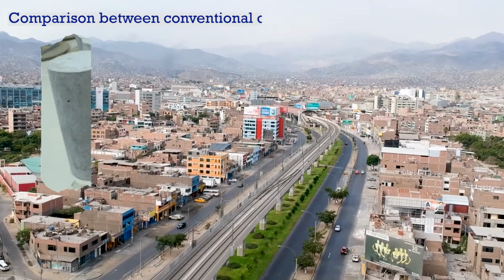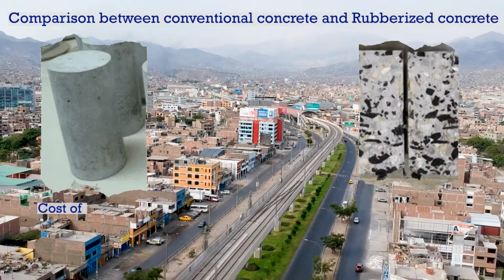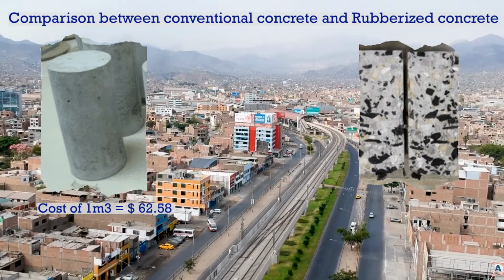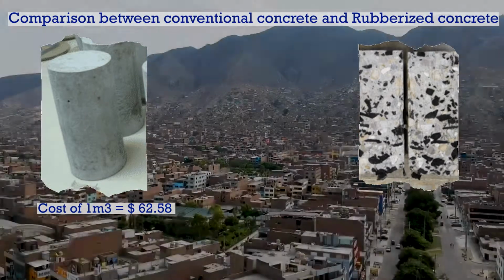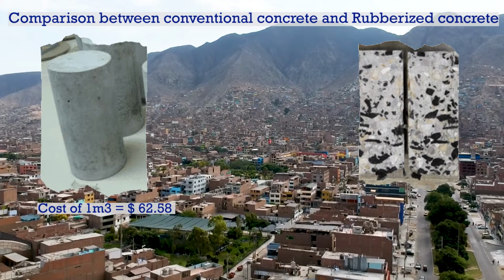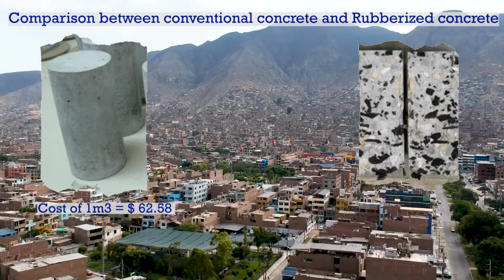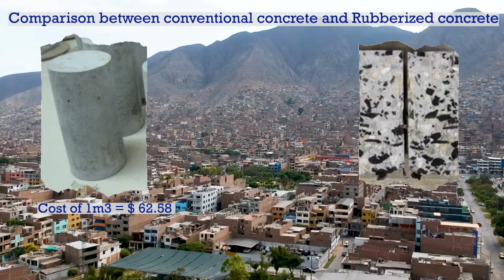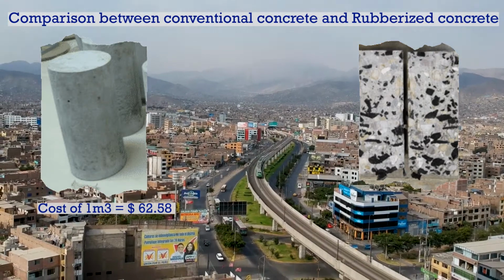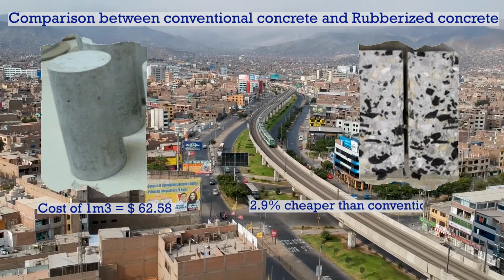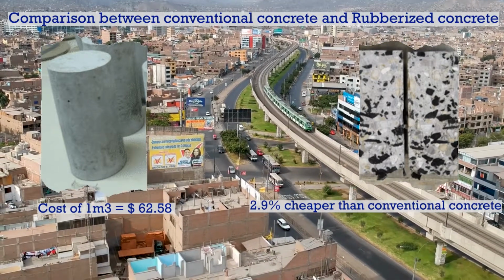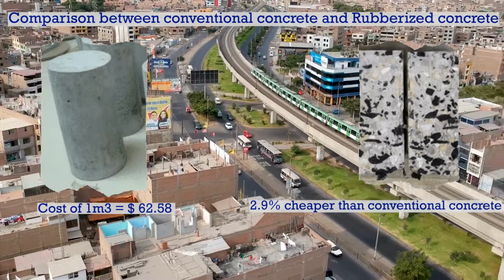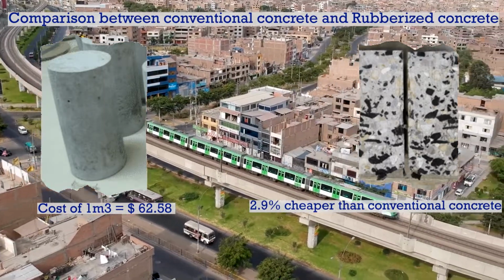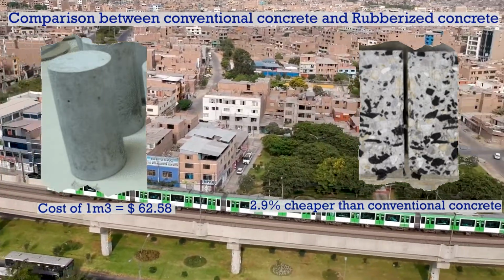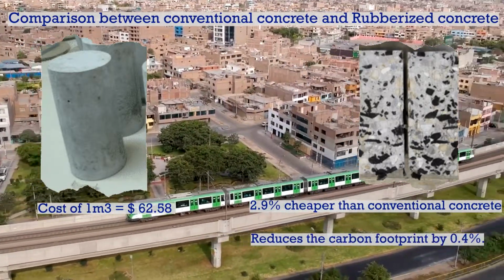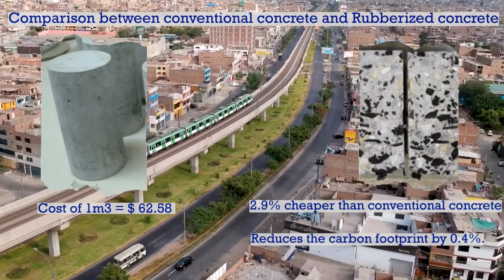Comparison between conventional concrete and rubberized concrete. The cost of a cubic meter of conventional concrete is $62.58. Its strength is from 170 to over 400 kilograms per square centimeter. However, rubberized concrete is 2.9% cheaper than conventional concrete. Its strength is from 170 to 250 kilograms per square centimeter. Also, rubberized concrete reduces the carbon footprint by 0.4%.